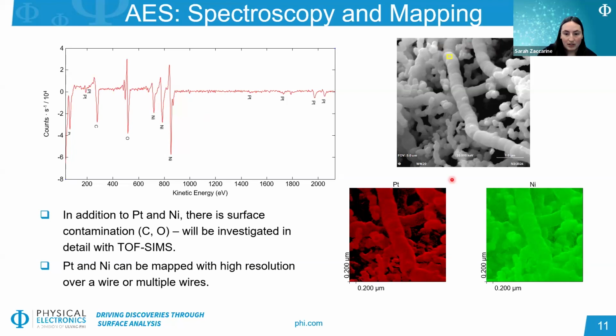And here's another image, slightly more zoomed in, of some individual wires. And then we're also going to use this to map the platinum, which is again the surface coating, and then the nickel. And another thing we noticed from this, the fact that we are detecting that nickel, which again is coming from that core wire, we either might have some movement of the two metals, a diffusion, and or the platinum coating is thin enough that we're able to actually detect through it into some of that bulk nickel structure.